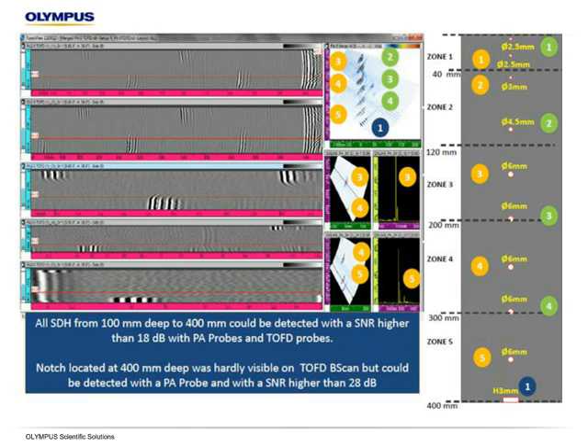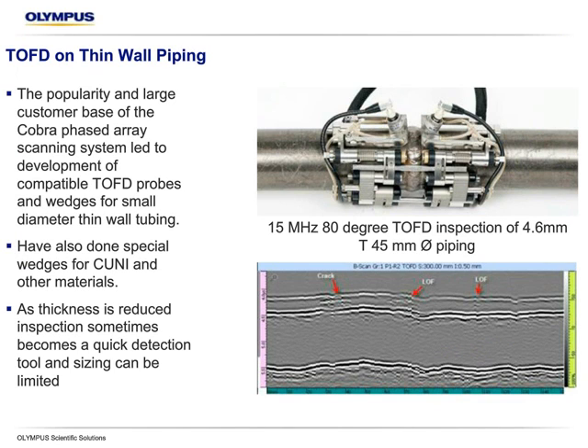Kind of the opposite, TOFD on thin wall piping. This can be a difficult application for ultrasound in general. This example is 4.6 millimeter thick, 45 millimeter diameter piping. We have specialized wedges due to the popularity of our Cobra system for weld inspection. We decided to add TOFD for things like corrosion erosion evaluation, as well as just to have a complementary TOFD inspection for flaw detection.